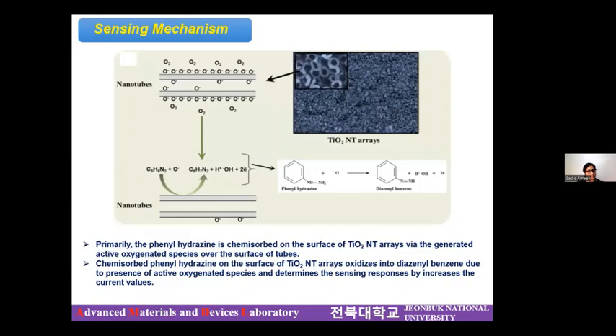And this is the brief description of how these TiO2 nanotubes have been effectively applied for chemical sensing, because here phenylhydrazine is the chemical that we have detected through these TiO2 nanotube arrays. The phenylhydrazine first got chemisorbed over the surface of the TiO2 nanotubes, and then it generated oxygenated species over the surface of the tubes.